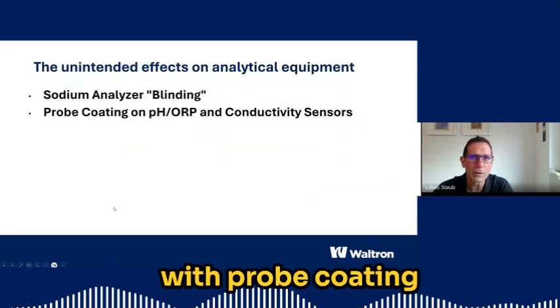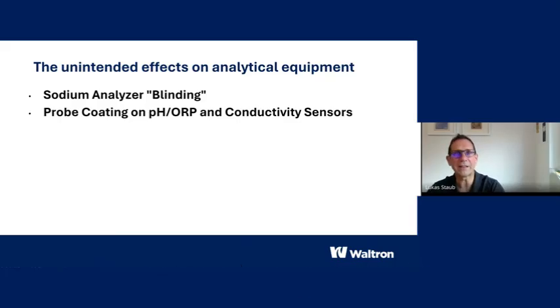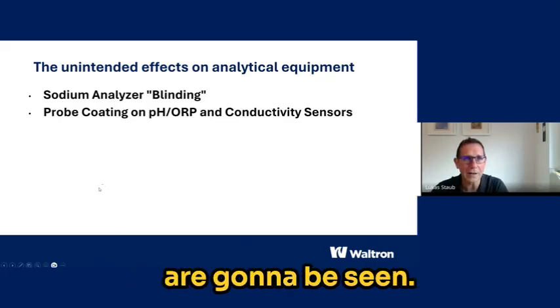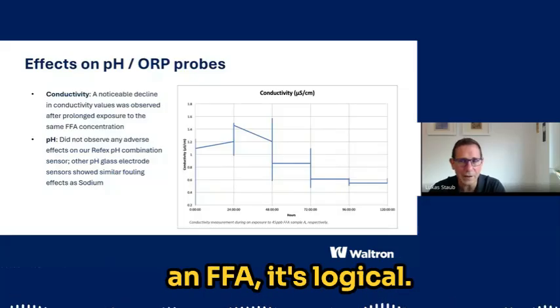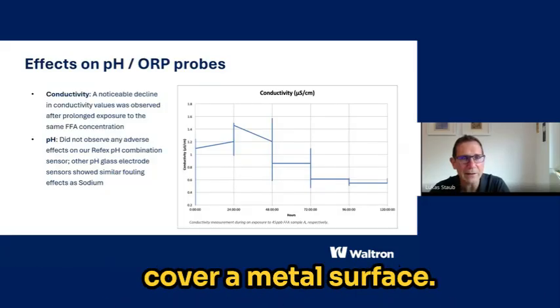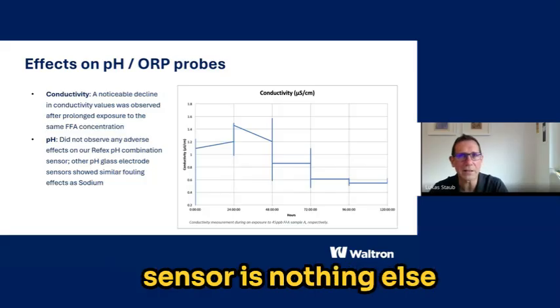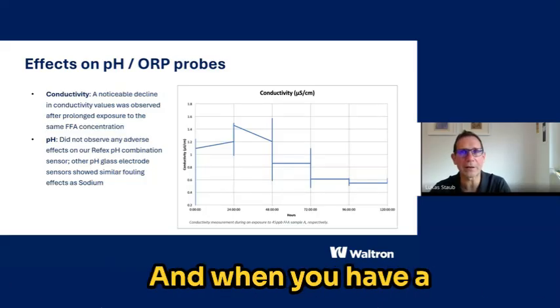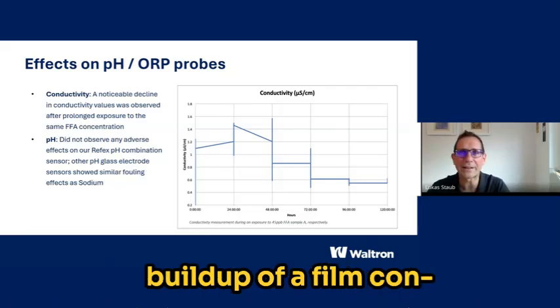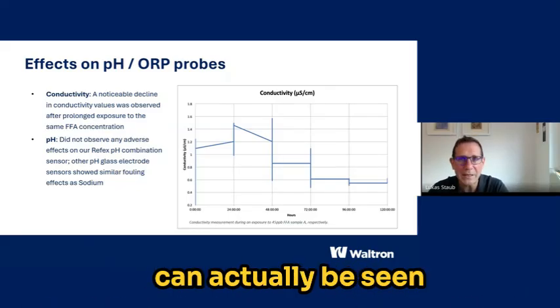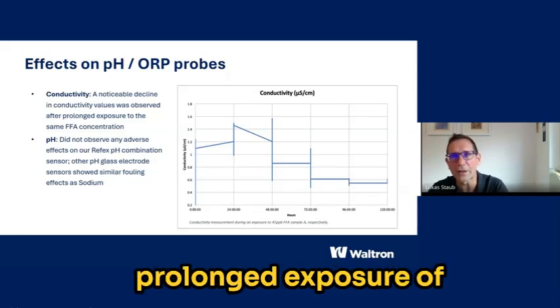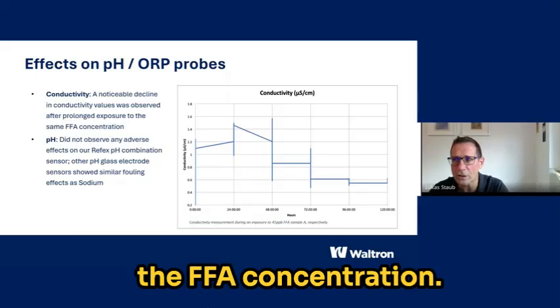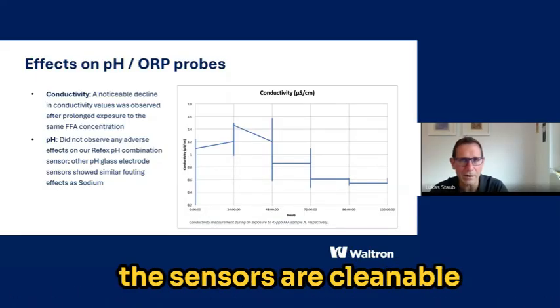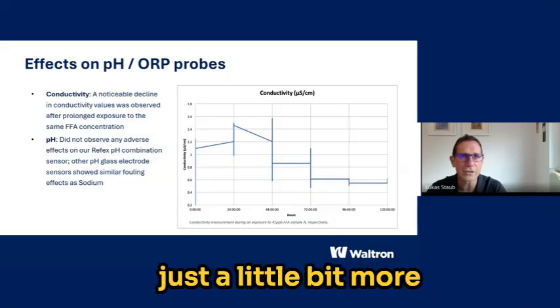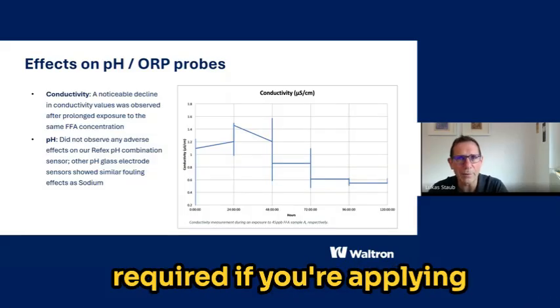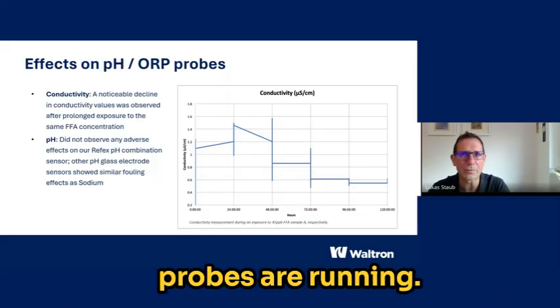I'm going to continue with probe coating on pH and ORP and conductivity sensors. Again, the same effects are going to be seen. So when you apply an FFA, it's logical. This is supposed to cover a metal surface. A standard conductivity sensor is nothing else but a metal surface. And when you have a buildup of a film, conductivity values can actually be seen to be affected with a prolonged exposure of the FFA concentration. The good news is that the sensors are cleanable very easily, so there's just a little bit more maintenance maybe required if you're applying an FFA to make sure that your probes are running.